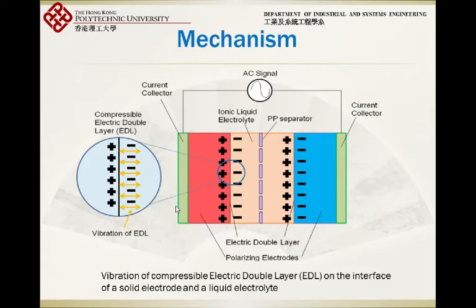So what if we try to apply AC to this interface? It was actually found a long time ago for the electric double layer: when you apply AC, this double layer can vibrate and generate sound. However, because this distance is very small, the sound generated is also very small. So this is where the graphene oxide or graphene porous structure plays an important role, because we can pack hundreds or thousands of layers of this 2D material, so we can accumulate this minimum displacement to become something that can generate more power delivery for ultrasonic applications.